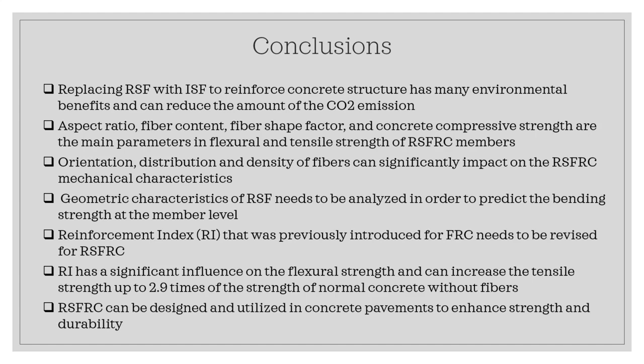Orientation, distribution, and density of fibers can significantly impact the mechanical characteristics of recycled steel fiber reinforced concrete. This was shown by a few experimental studies that we did in our lab, and also many previous studies that were conducted before. Geometric characteristics of recycled steel fiber need to be analyzed in order to predict the bending strength at the member level. Why? Because aspect ratio is one of the major parameters in changing the reinforcement index.